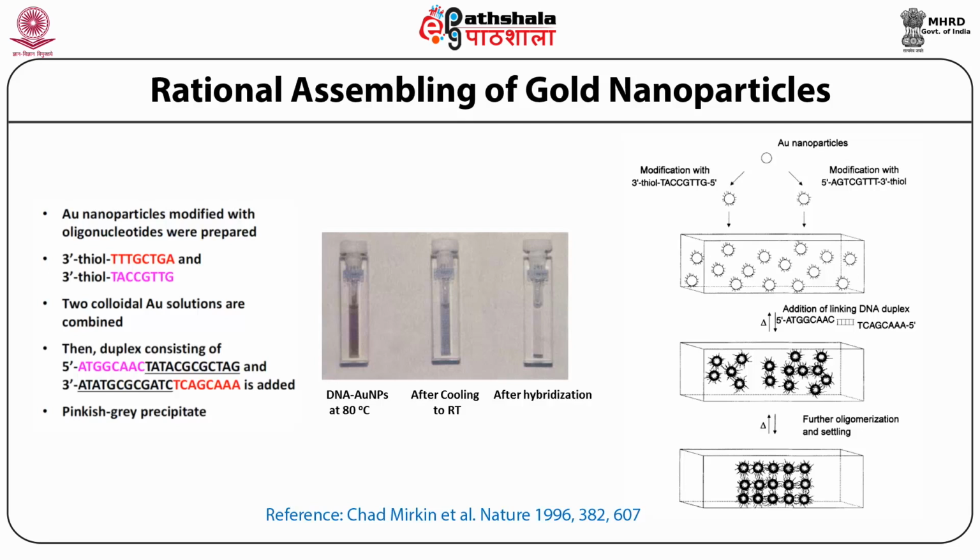Now when another DNA duplex with a sticky end, which is complementary to each of the ligands, was added, it assembles all the DNA nanoparticles through hybridizing the sticky ends and the complementary strands, forming an assembled structure. What we see is that the entire assembly precipitates, and the surface plasmon resonance changes from red color to bluish color, and it eventually precipitates.